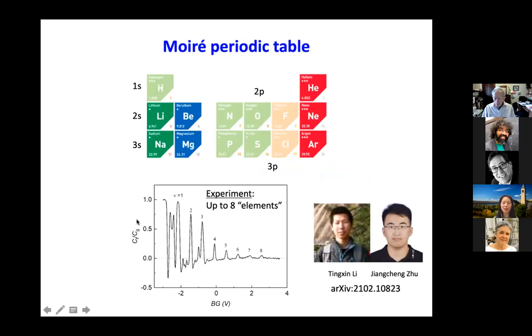What you are looking at here is something we call a penetration capacitance. You just have two plates, and you have your sample in the middle. If your sample is conducting, it will screen out the field, and then you measure something very low. If the system in the middle is insulating, then the field will have no trouble penetrating, and you get a high number. Every time we load an integer number of electrons into those traps, we get peaks, insulating states coming out. We have realized up to 8 elements, so 8 electrons per trap.